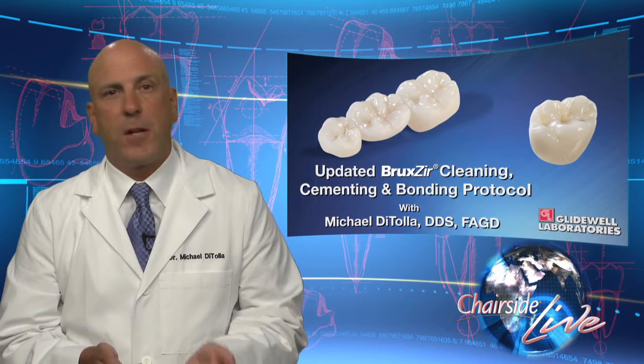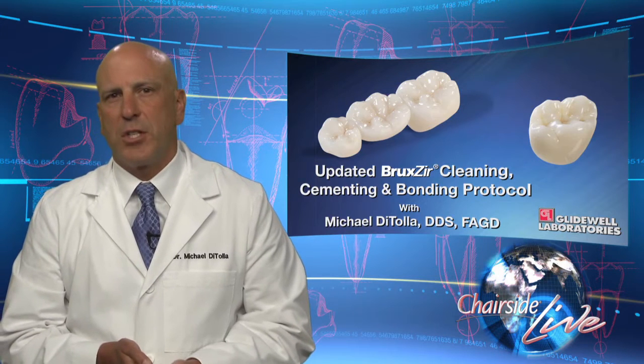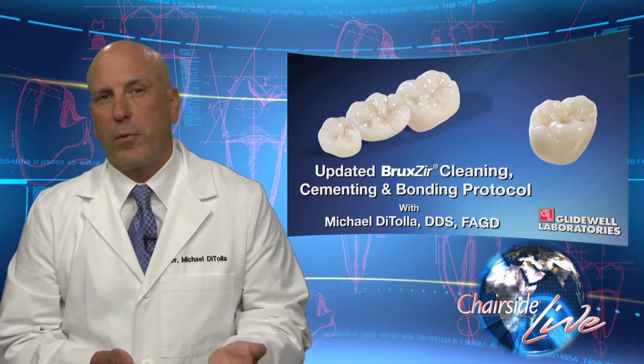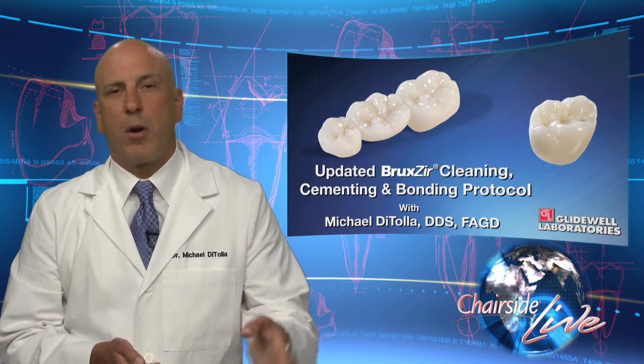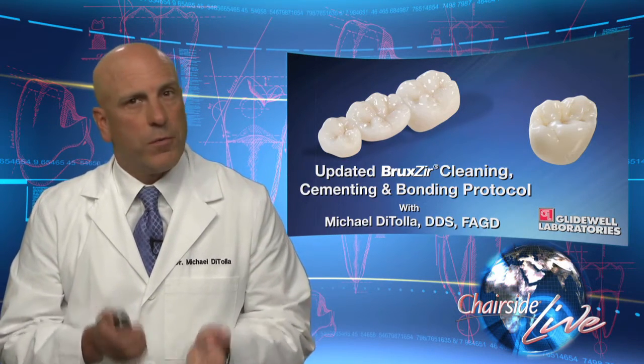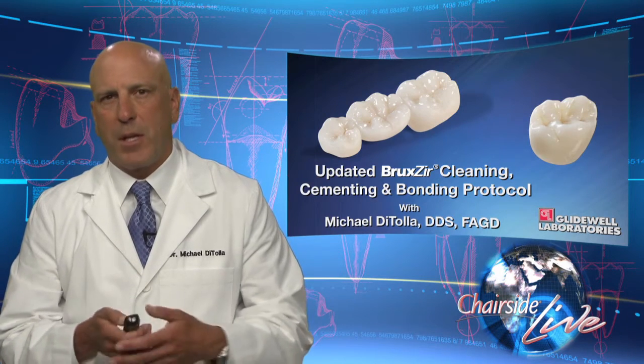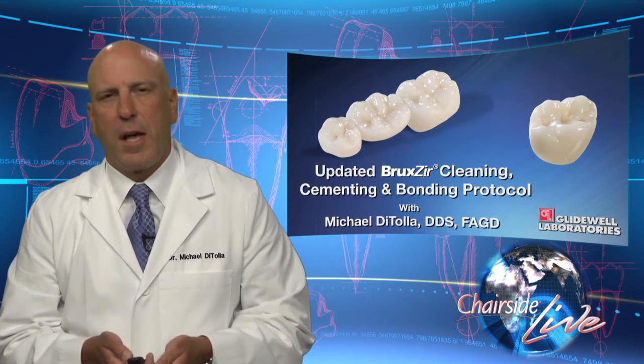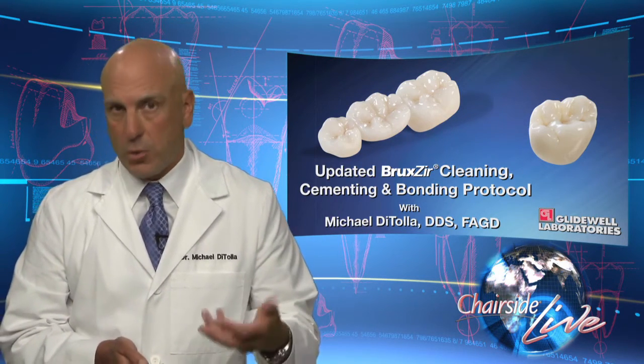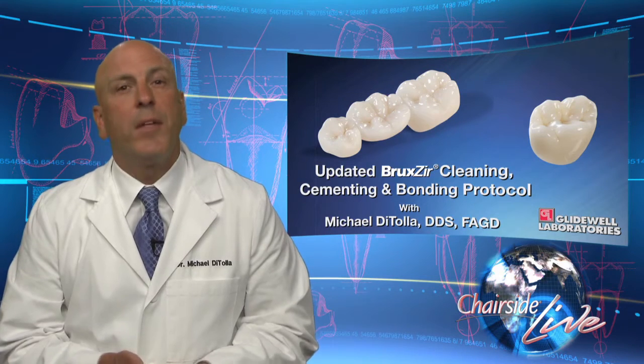It's been pretty simple, whether we had feldspathic porcelain veneers or crowns, or if we had a leucite-reinforced porcelain such as Empress. When it came time to put these restorations in the mouth, they had already been etched with hydrofluoric acid at the laboratory, so it was a matter of trying them in with or without try-in paste. We'd try them in the mouth, verify the marginal fit, and the aesthetics. Usually we'd be using a water-soluble try-in paste, so when it came time to clean it out, we could just take our air-water syringe and clean everything out. Some dentists would use a 37% phosphoric acid gel to clean the inside of the veneer out as well, and that would work too.